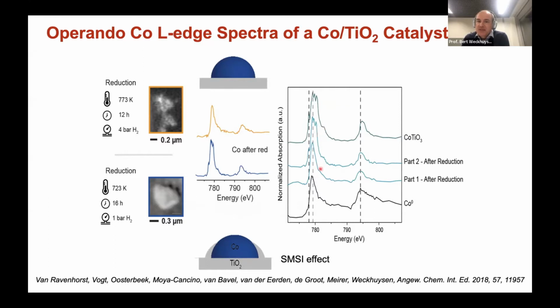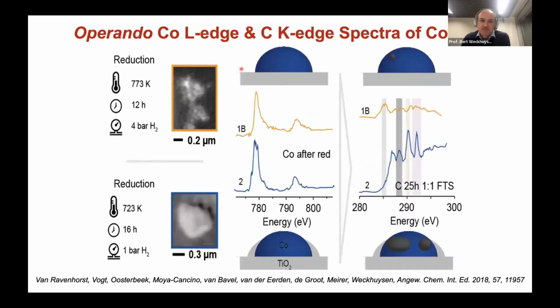Do you do it in another way? You have mainly cobalt metal. So seemingly this titania, you can really play what we call strong metal support interaction. The titania can creep on the cobalt or just leave the cobalt free for catalysis.